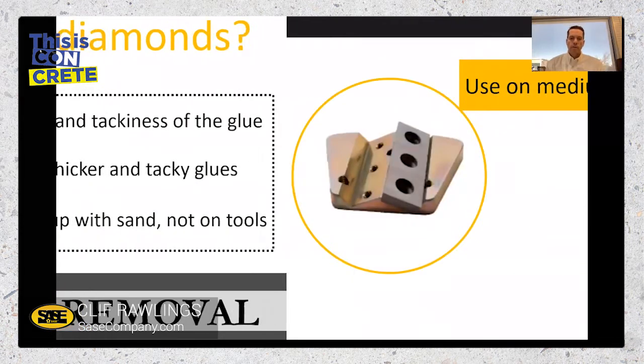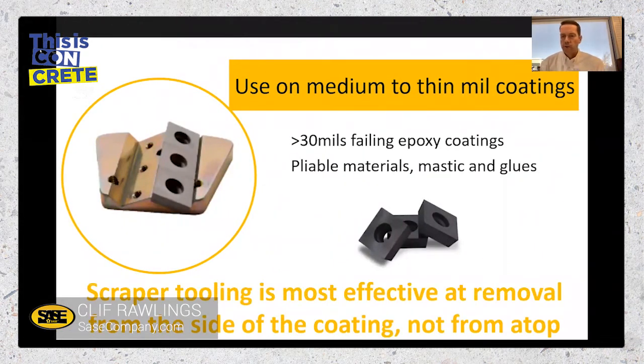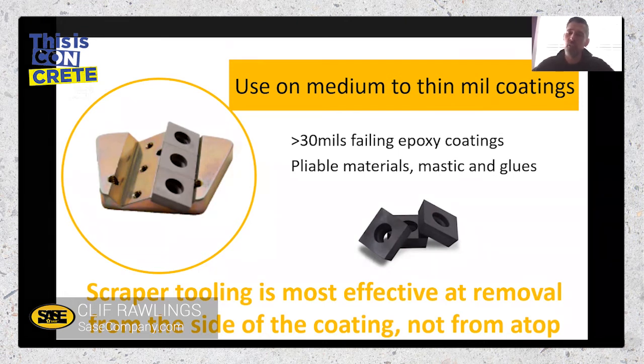And there isn't enough water in the damp sand to create a problem for your vacuums if you're still running dry. That's correct. That's why I really want to emphasize damp, not wet sand, because it also gives the sand a little bit of weight. Previously, when we used just dry sand, we had to pull or slide the skirts up so that the dust extractor wouldn't suck all of your sand up before you had got the benefits of it getting mixed into the actual glue. So when we did that, it created even more of an airborne dust issue. So now we can actually leave skirts down. The damp sand is heavier and doesn't get sucked up as fast into the vacuums and gets mixed into the glue easier that way. So it really was a win-win.